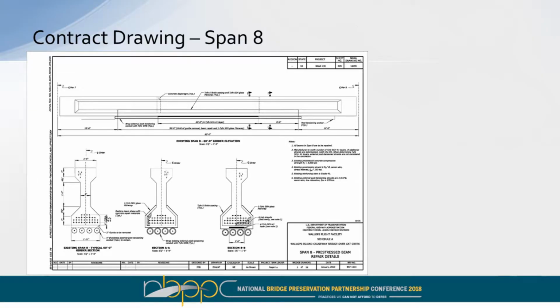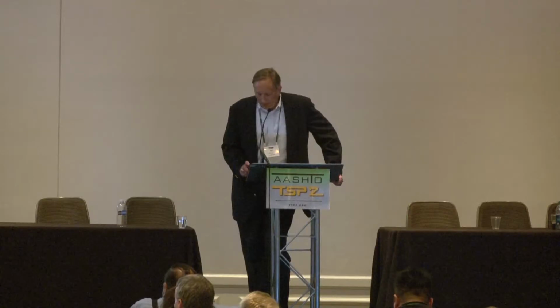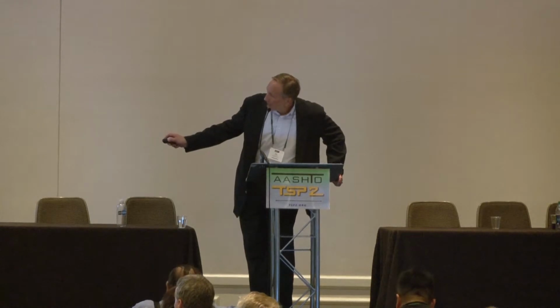So here's a shot of, I believe this is span 8, it's tough to read from this angle, where some of the loss of strength or flexure in the beams took place according to the last survey inspection. And you can see in this particular case, the beam that we inherited to repair came with about 2 inches of gunite on the bottom of the flange, and then below that were 4 external post-tensioning strands that were obviously anchored on either side of the beam.